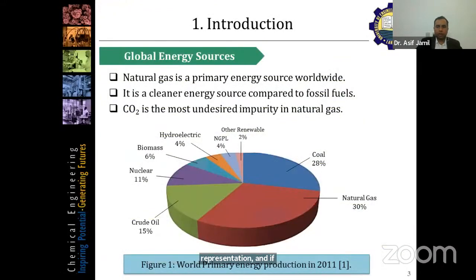If we look at the global energy sources, natural gas shares 30% of it, because it's considered a cleaner energy source compared to fossil fuels. The impurity it contains is CO2, which is highly undesired because it reduces the calorific value of natural gas. In addition, in the presence of water, it can corrode the pipeline. So CO2 separation is very important for natural gas.